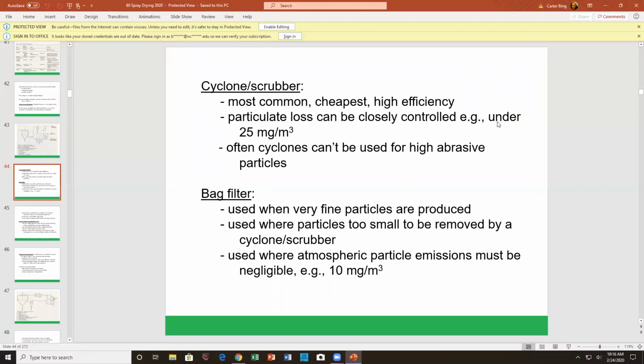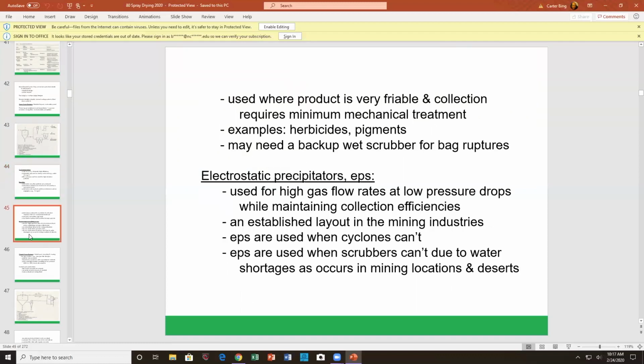Particulate loss can be closely controlled. 25 milligrams per cubic meter. Often cyclones can't be used for highly abrasive materials. Bag houses are used when very fine particles are produced, when particles are too small to be removed by cyclone scrubbers, and when atmospheric emissions must be negligible, at 10 milligrams per cubic meter. Used when the product is very friable and collection requires minimum mechanical treatment. Herbicides and pigments are examples. May need a backup wet scrubber for bag ruptures.